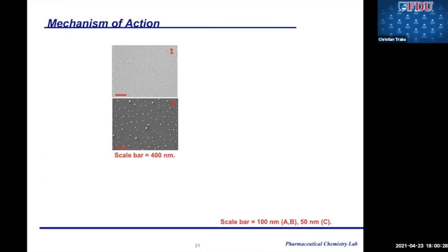Scanning electron microscopy was used to further visualize our surfaces, but at the nano level. The scale bar for these images, 1 and 2, is 400 nanometers. In these images, grafted surfaces, image 1, possessed densities of 48 micrograms per centimeter squared, and these coatings demonstrated uniform polymer brush coverage. Immobilized surfaces, or image 2, demonstrated evenly dispersed silver nanoparticles throughout the surface of the grafted material.